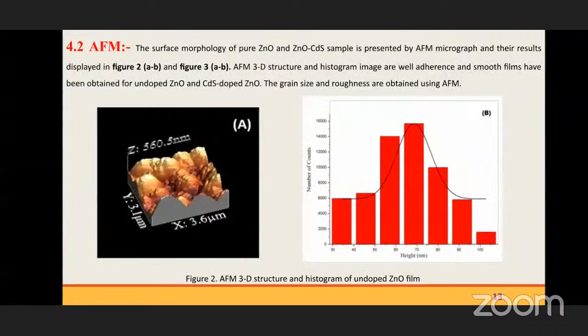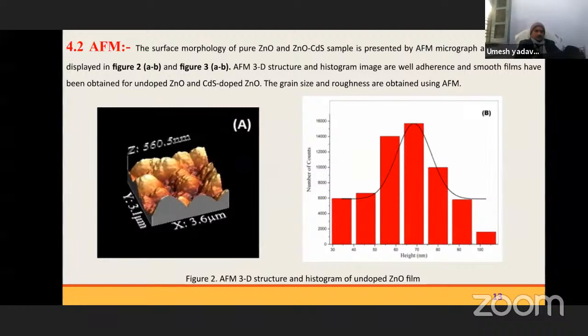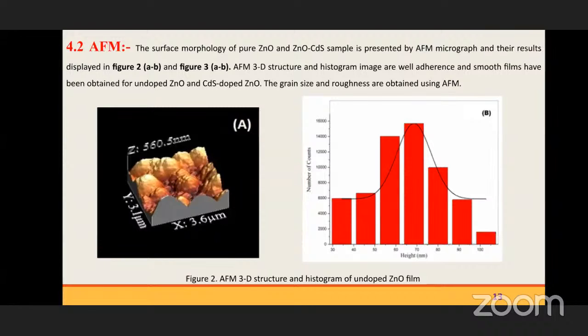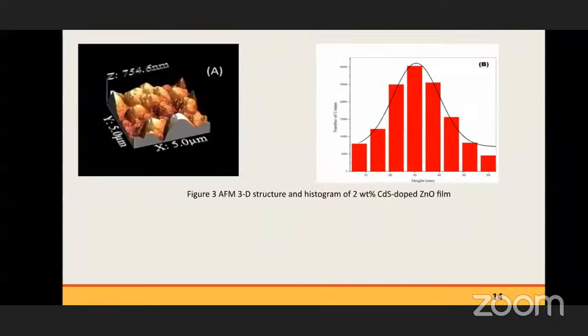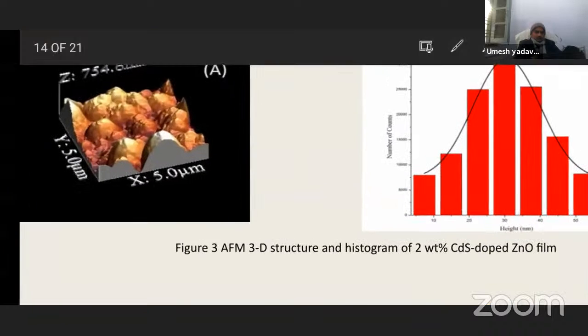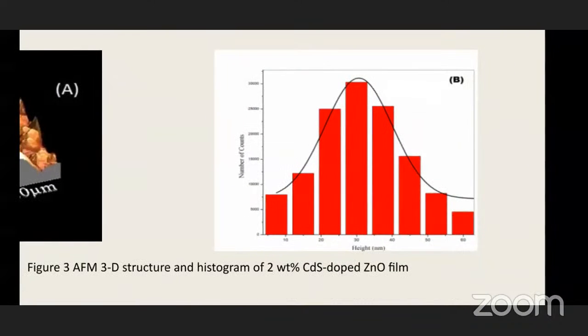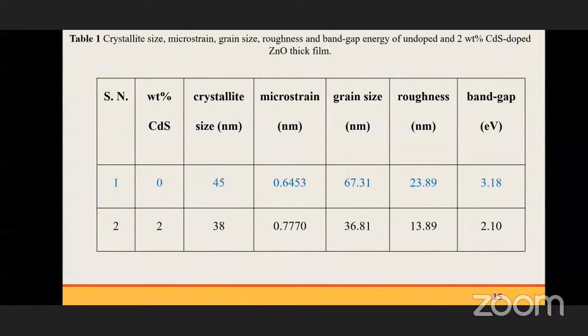Atomic force microscope. The surface morphological properties of ZnO and ZnO CdS are presented by atomic force microscopy, and the results are shown in 3D, three-dimensional, and histogram of the ZnO and CdS doped ZnO thick film. This is the 2% CdS doped ZnO, its three-dimensional image and its histogram. Here, crystallite size, microstrain, grain size, roughness, and band gap energy of undoped and CdS doped ZnO are presented.